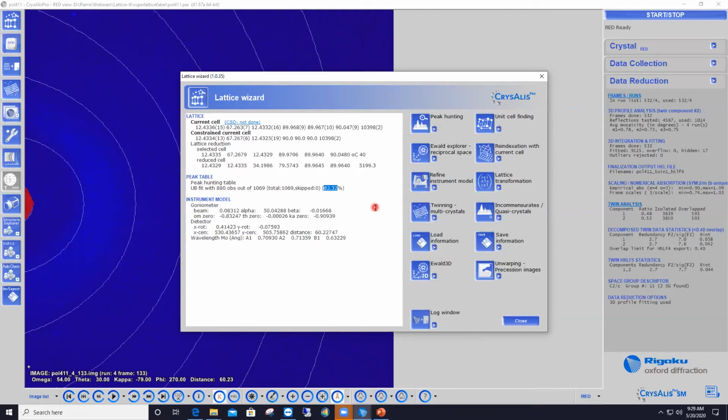So at first glance, many people would tell you that your indexing just worked fine. Except if you look at the unit cell parameters, something is weird, because I've got a long unit cell edge of 67 angstroms, which is more like a unit cell edge for a protein structure and not for a small molecule. That makes for a huge unit cell, especially for a compound that has barely 20 non-hydrogen atoms. So something is a bit fishy there, and of course, then you want to look at your reciprocal space.